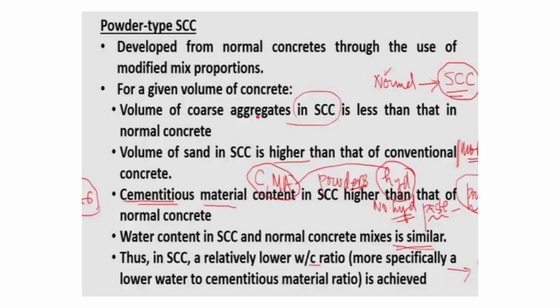Okay, so we have gone through all this in the last lectures. The volume of sand in SCC is higher than that of conventional concrete, because the fines are more in SCC as compared to concrete. Therefore, the aggregate is less in SCC as compared to normal concrete. Then the cementitious material content in SCC is higher than that of normal concrete. And the water content in SCC and normal concrete mixes is similar, as we saw in the example before.